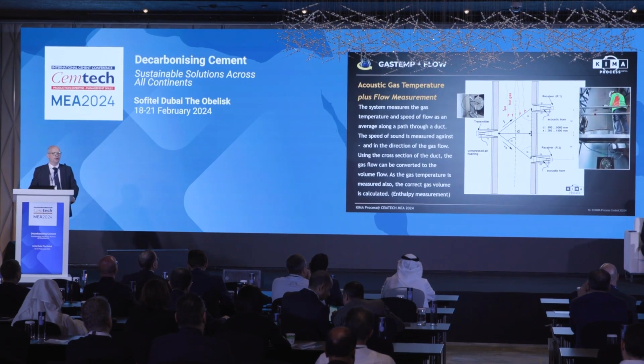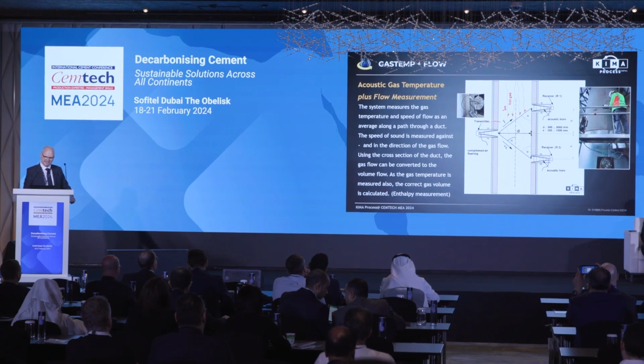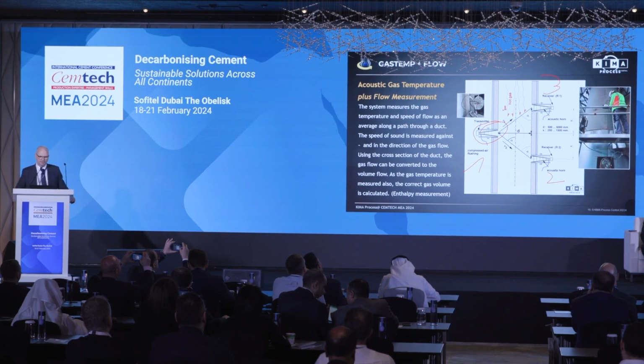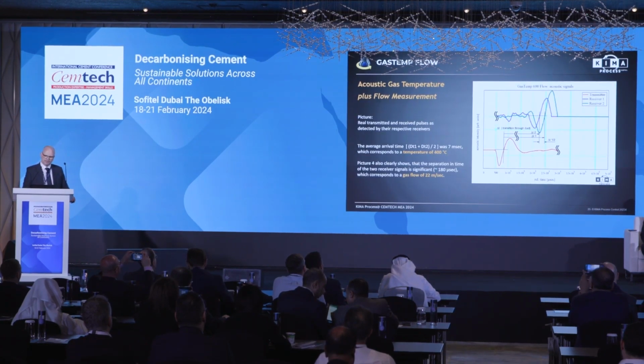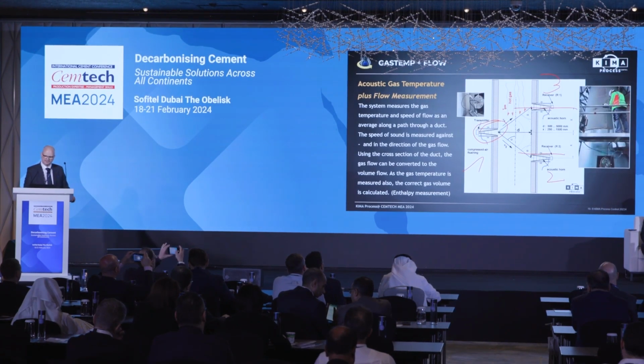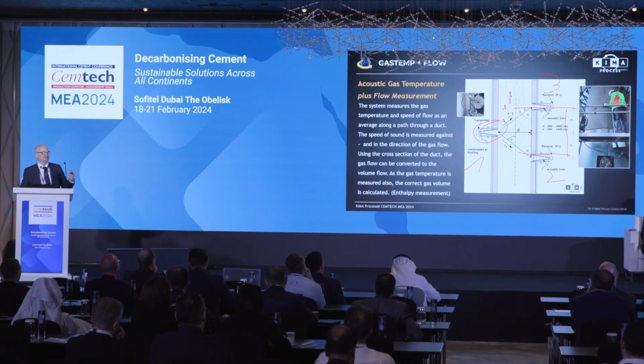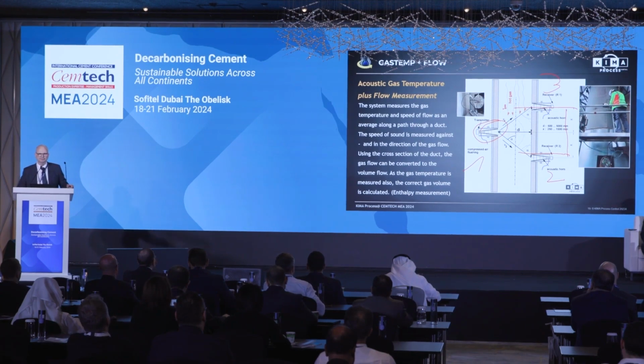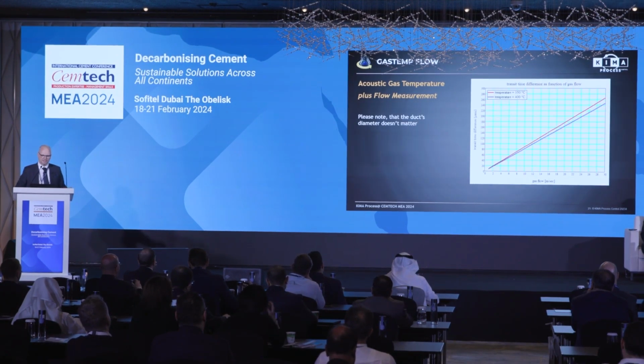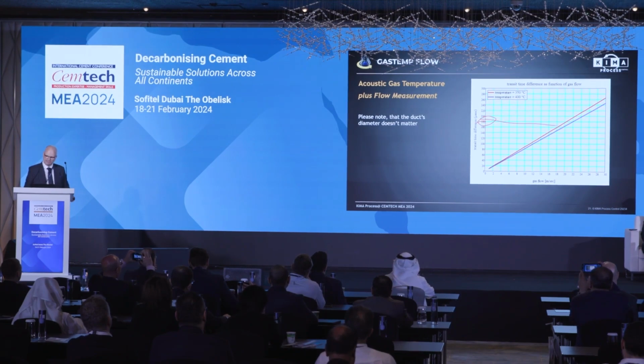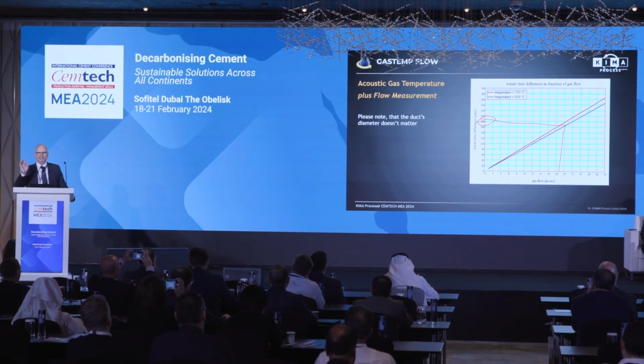The principle of the flow measurement is very similar. We use the same sensor, but not one or two microphones; we have a third microphone. This microphone is used to measure the time over a defined distance. And you, as technicians, know that a defined distance with time gives speed: meters per second, centimeters per second. And this is what we do. We measure the time and we can give you the exact gas flow. Again, we measure time, not gas flow, not pressure or something like that.